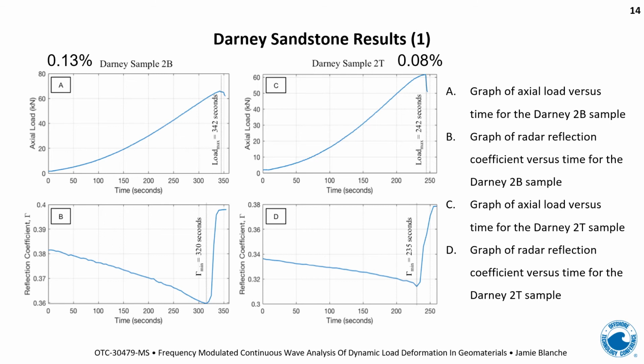Now this is neatly reproduced in the second sample. You're seeing again the increase of the load to the fail point, and again in advance a turning point in the reflection coefficient. What's worth noting at this point is the 0.13 moisture content corresponds to a higher reflection coefficient than the 0.08 moisture content. 0.08 moisture content corresponds to a slightly lower reflection coefficient. That's in keeping with the understanding that more moisture within the sample will give you a higher reflection coefficient.